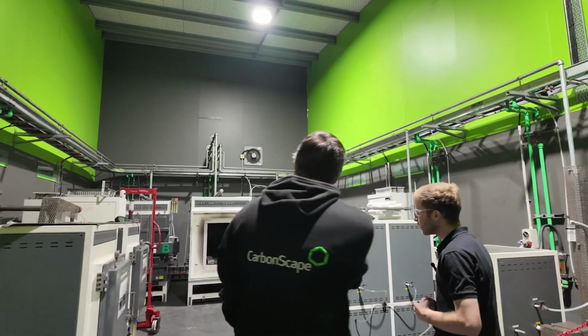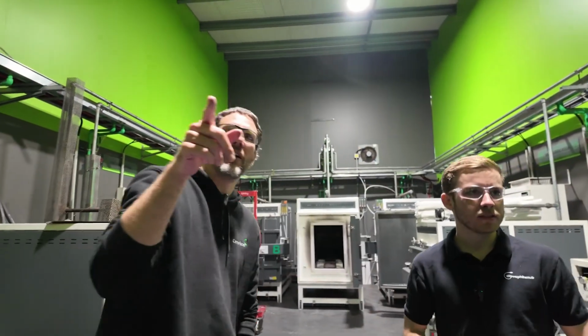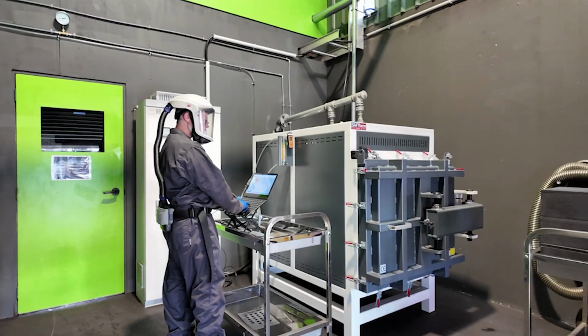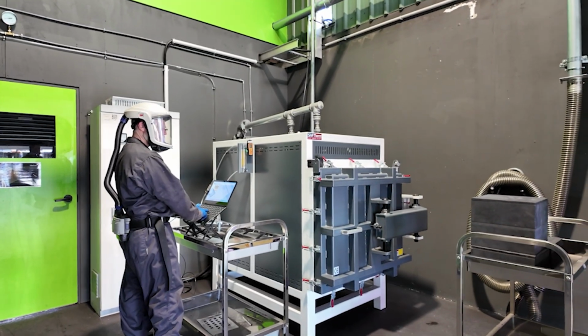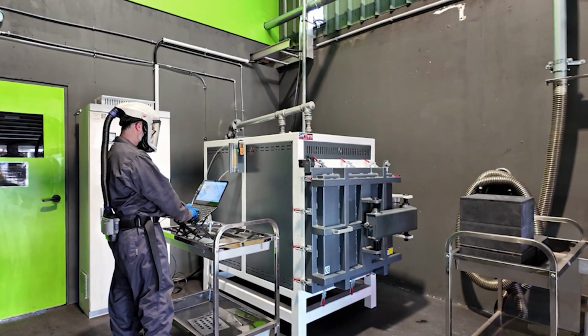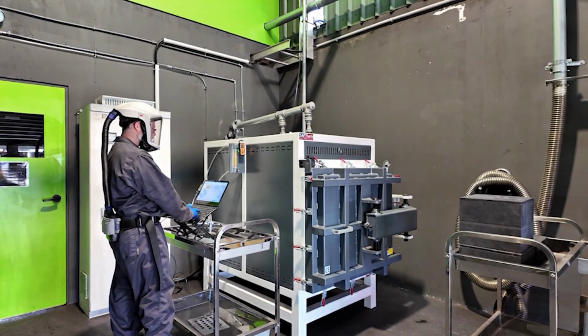Once the biochar is combined with the catalyst, it enters the RHK, where the material will sit in saggers and is heated to around 1500 degrees. And as it moves through the RHK, it slowly transforms into graphite.